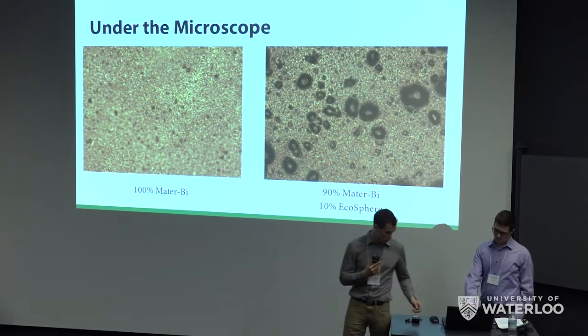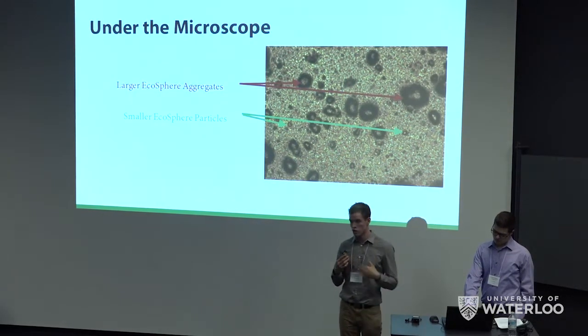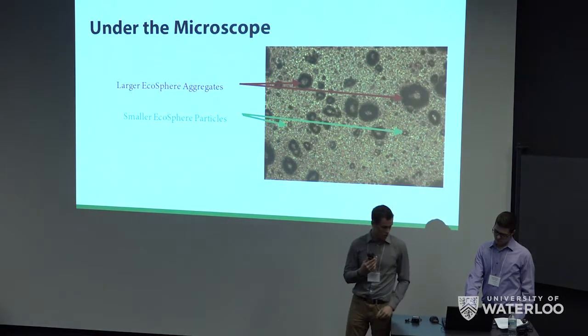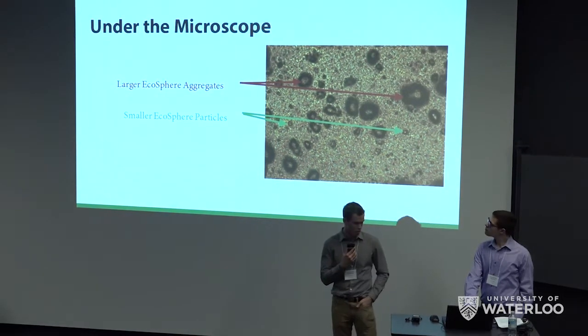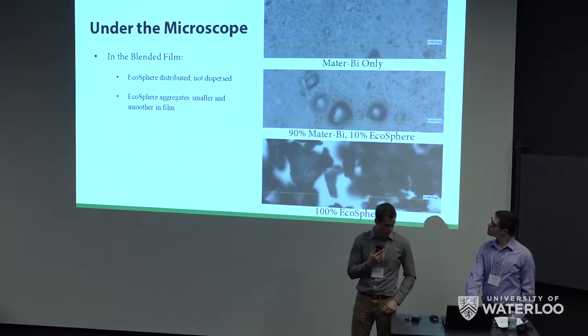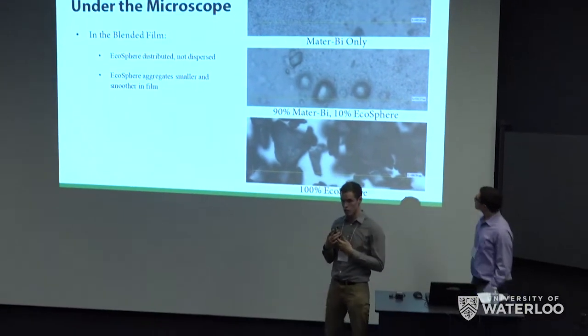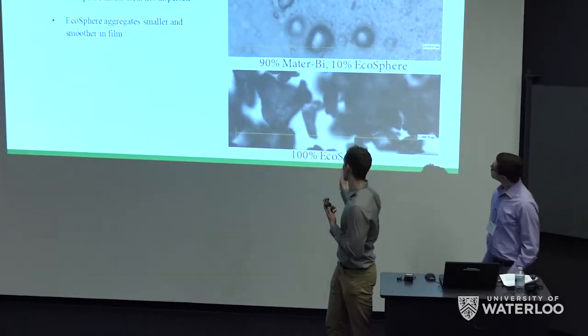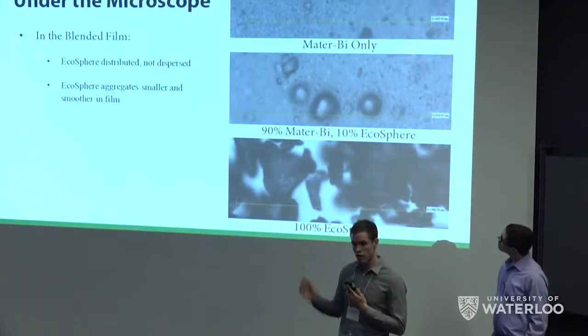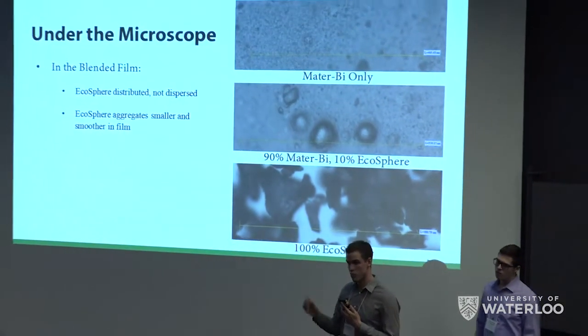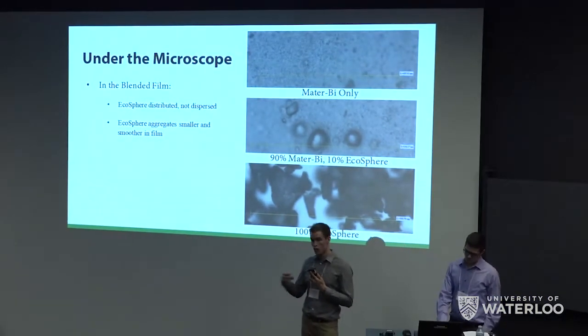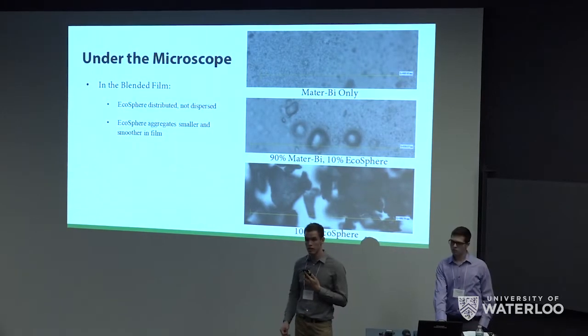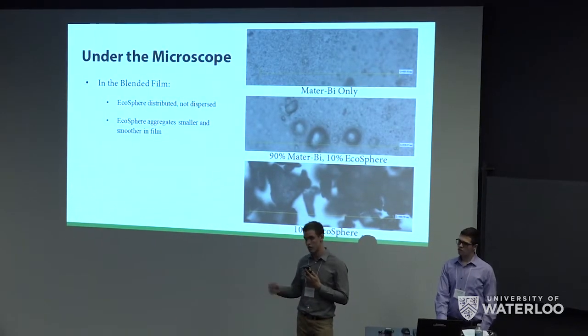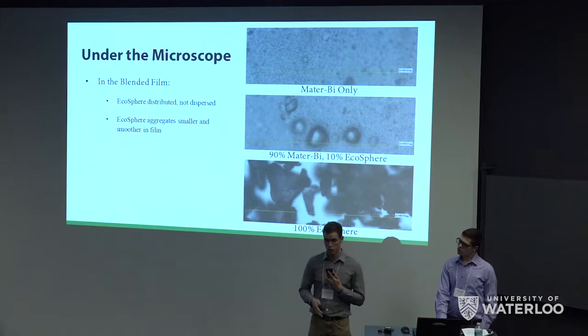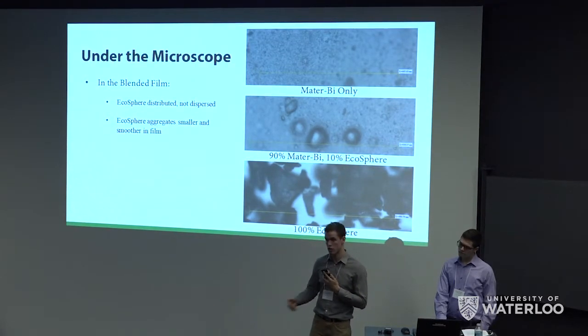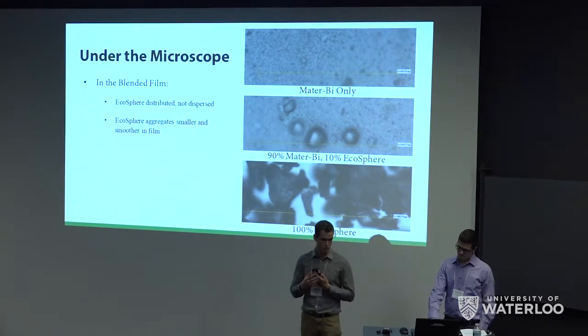It also has smaller particles distributed throughout. So this shows that we did start to distribute the particles, but it was not a completed process. One very good thing is when we looked at images of Ecosphere by itself and Ecosphere in our resin, it was much smaller and much smoother. So this indicates the forces were starting to act and degrade this, but we need either longer time in the extruder, which is not possible with our current extruder, or higher shear force, which again was not possible with the extruder that was available to us.